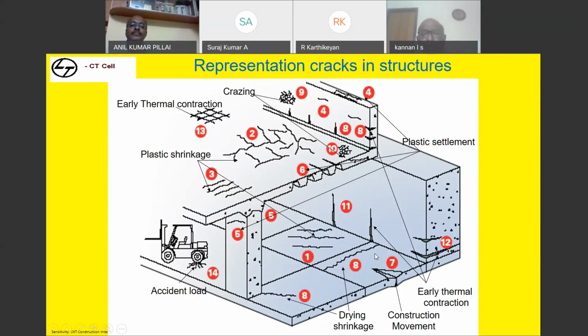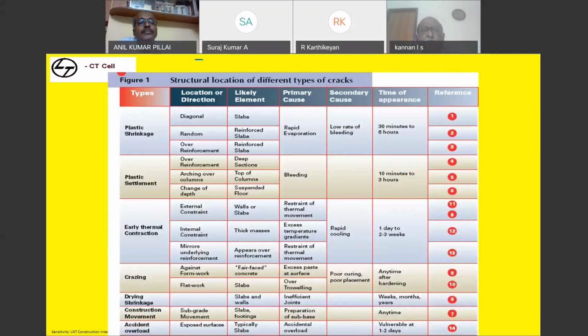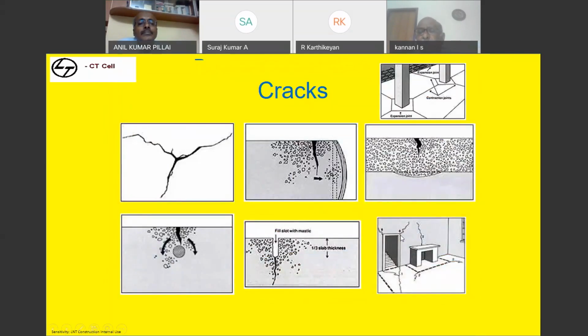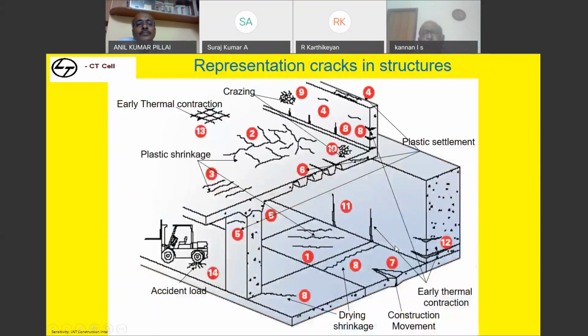This is a drying shrinkage crack, because normally with drying shrinkage cracks, if you see the doors and window frames that we have fixed, after fixing them you can find some cracks in the walls, because the thermal expansion of this and this is totally different. When this is shrinking, it is inducing a crack here. This is all drying shrinkage cracks. Okay. And these are all thermal cracks. So you are able to see.